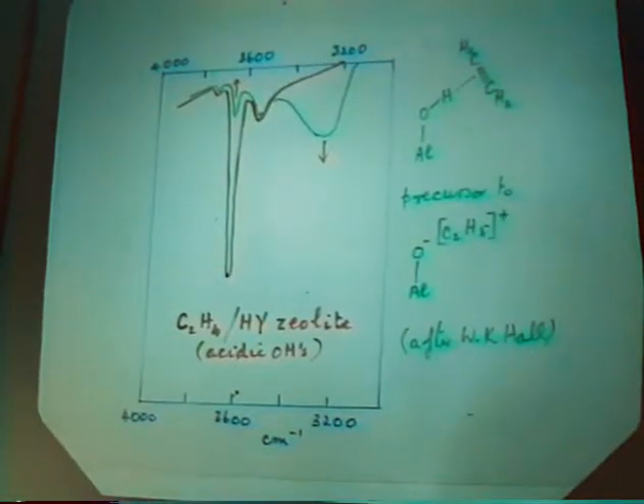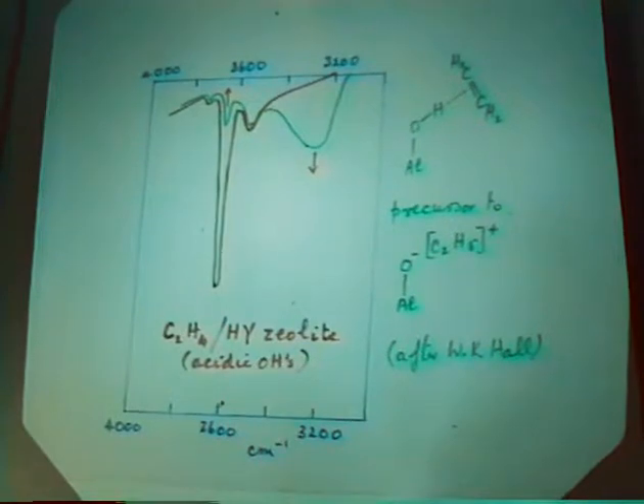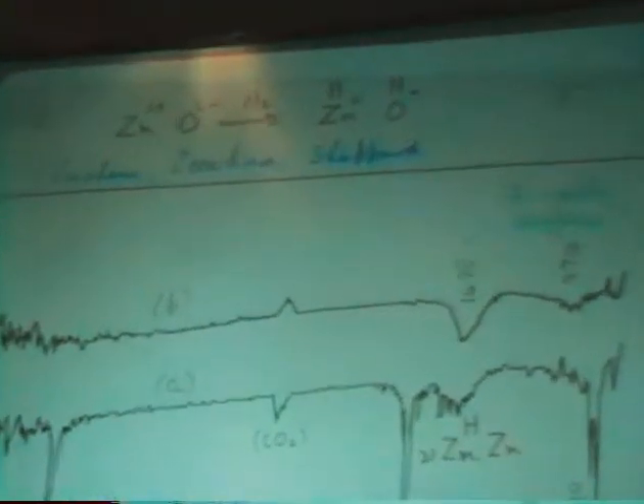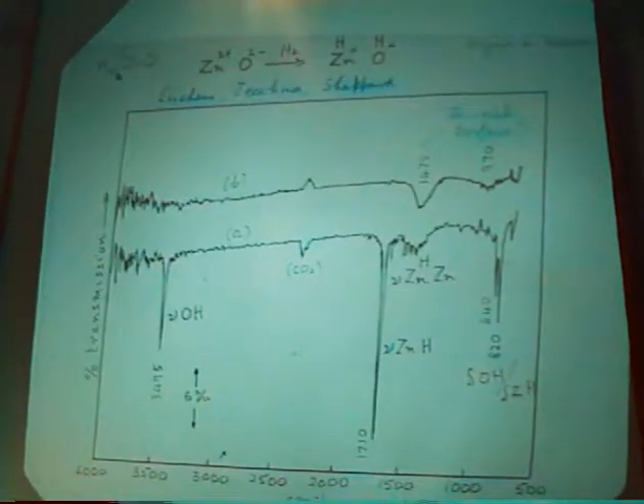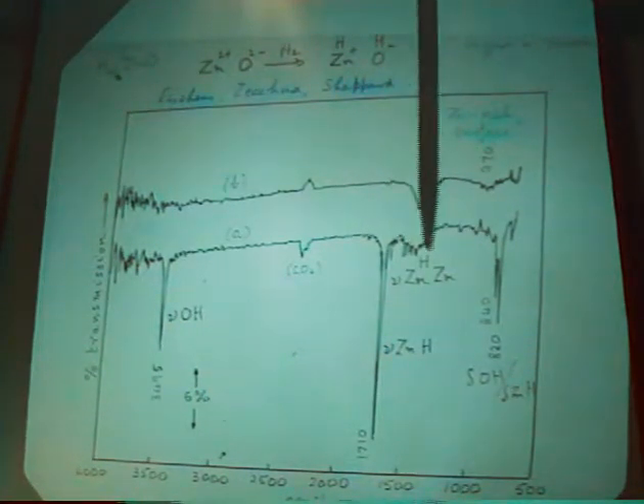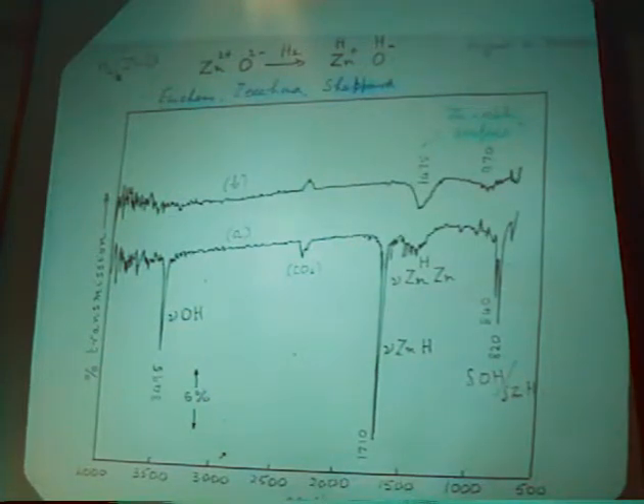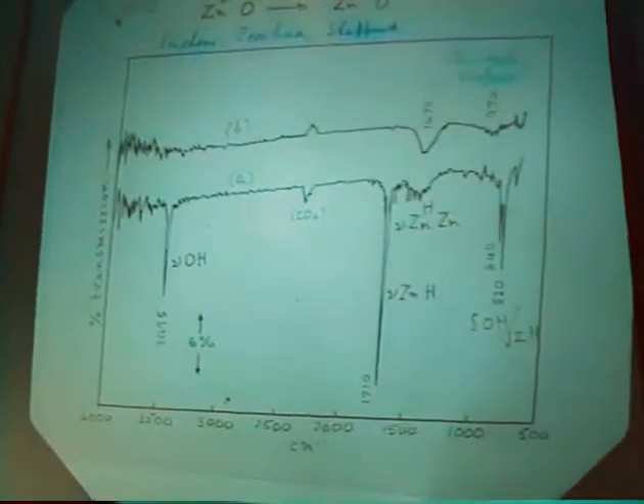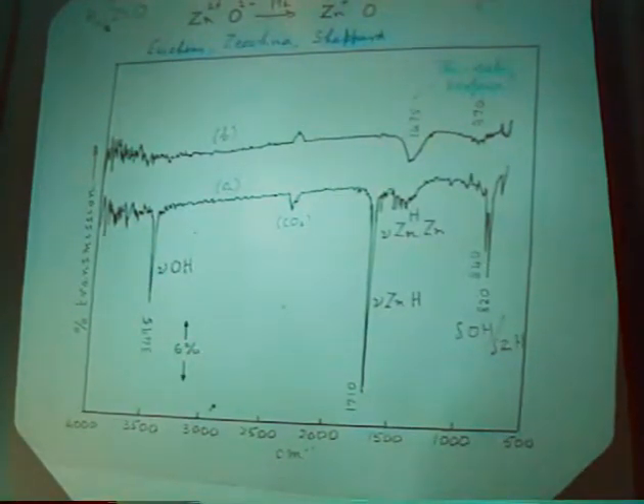This spectrum was shown by Keith Hall yesterday. It's one of my favorites, a good strong hydrogen bond from an acidic OH to a hydrocarbon. I always like that spectrum. Bob did some very nice work from hydrogen on zinc oxide, and again, as Keith mentioned yesterday, leading to heterolytic dissociation. Nowadays, you can remeasure those spectra with FT and get down to the angle deformation region and see the OH deformations as well as the ZnH and OH stretches. And in this case, and this was initially the work of Zecchina, which we followed up, there is an additional species which we think is the bridge species. When you look at an oxide surface, some of the faces have equal numbers of oxide and zinc ions. Others are zinc-rich or oxygen-rich, and one suspects that this bridge species is on one of the zinc-rich surfaces.